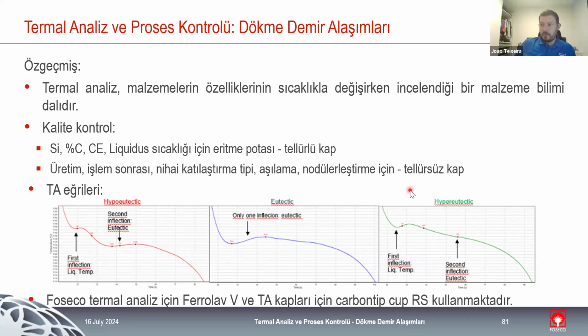And it is important for quality control because we can use it in the melting ladle for control of the silicon, carbon, liquidus temperature with the cups with tellurium. And we can use it in production after treatment, after magnesium or inoculation treatment using the cups without tellurium. And we can check different parameters to check if the inoculation process or the non-inoculation process was okay, and if you have a good melt to produce and to have sound casts.